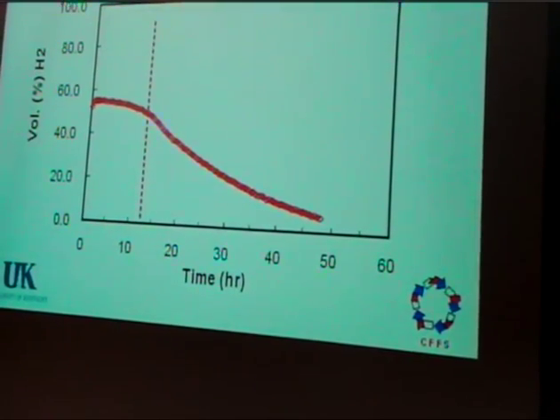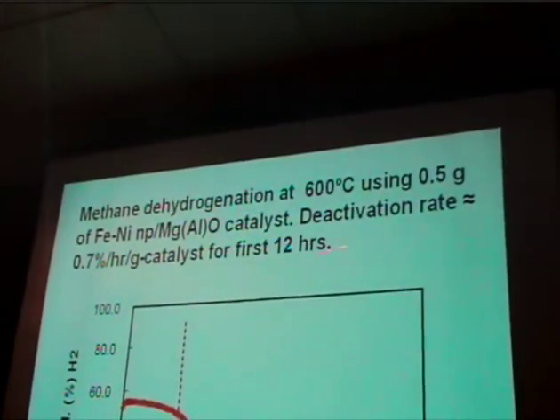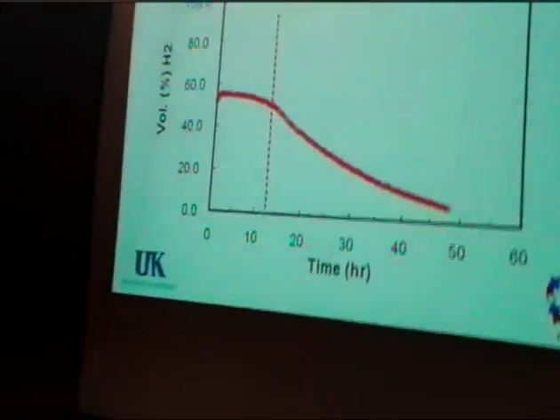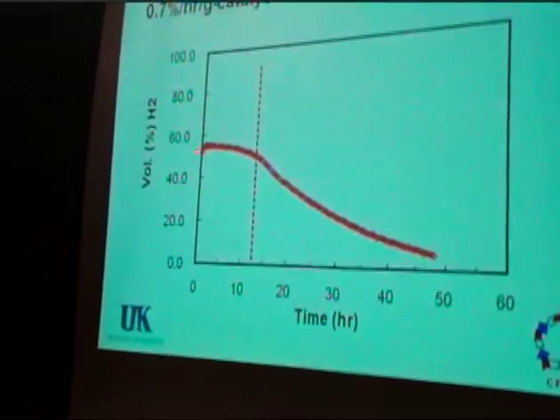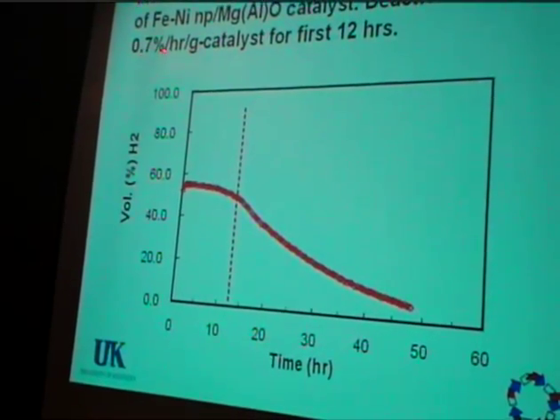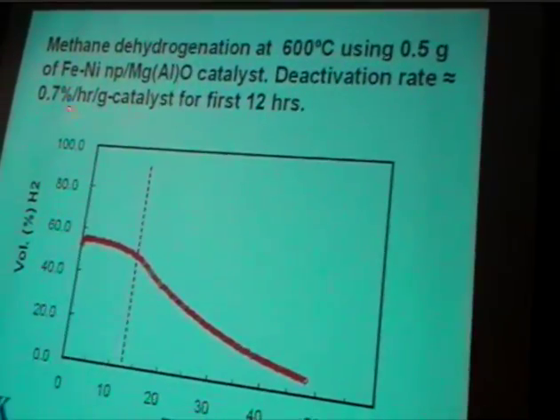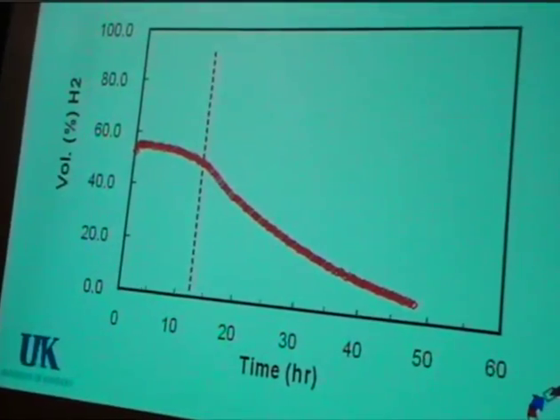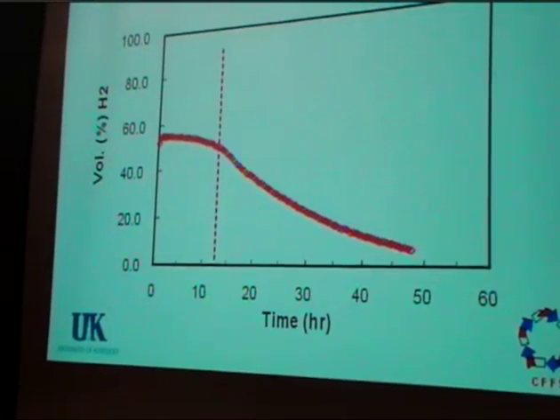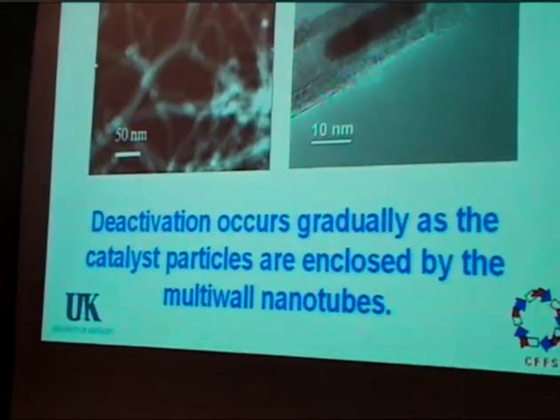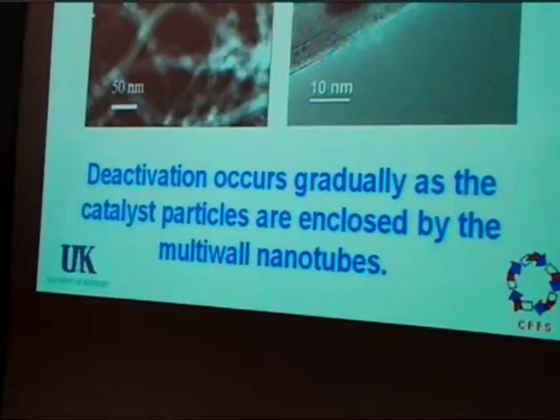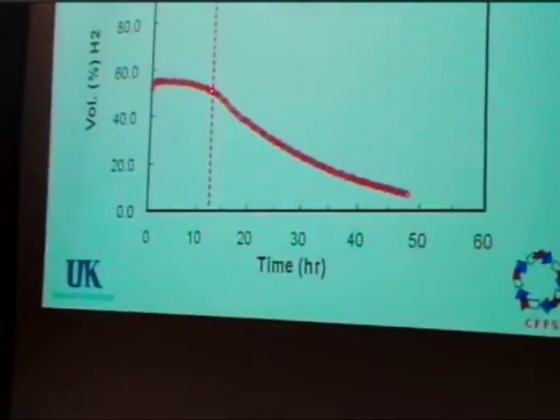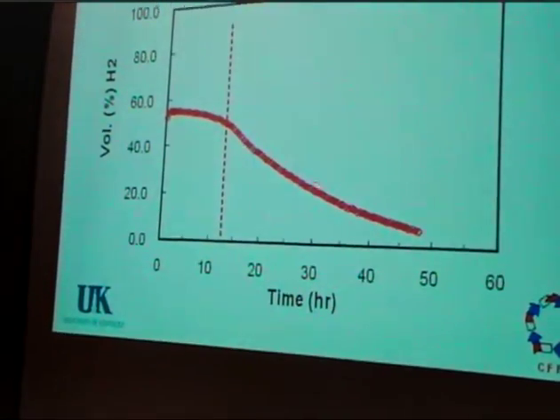And to look at the stability of the catalyst, we looked at a little bit larger size catalyst, a half a gram, and the deactivation rate is about 0.7% per hour per gram of catalyst. That compares to the earlier rates that I quoted, which were about 3% per hour. Deactivation, you can see it starts slowly deactivating after about 12 hours and gets down to terminal levels at about 30 hours.